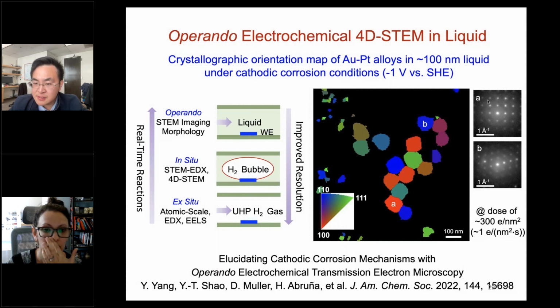In this case, it is actually counterintuitive because we thought noble metal would be indefinitely stable at reducing potential, but actually it's not. The underlying mechanism can be that alkaline cations in solution can stabilize reaction intermediates in the formation of metal hydride. Eventually, that contributes to the formation of this cathodic corrosion.